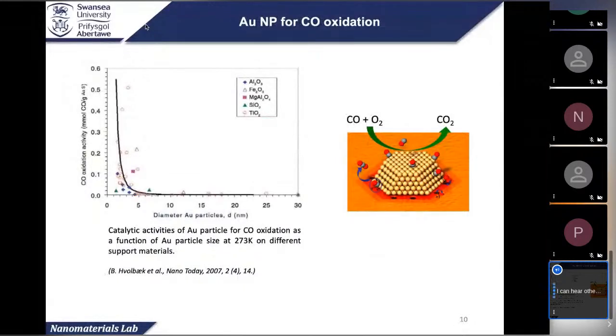It has been widely known that gold is a very good catalyst for CO oxidation. But the problem, if you look at the graph on the left, and the substrate we chose is silicon dioxide, the green one, there's basically no activity on this substrate, regardless of the size. But for other supports, you get very good catalytic activity when the size is below 5 nanometer. So gold is a very good example of size effect in catalysis.